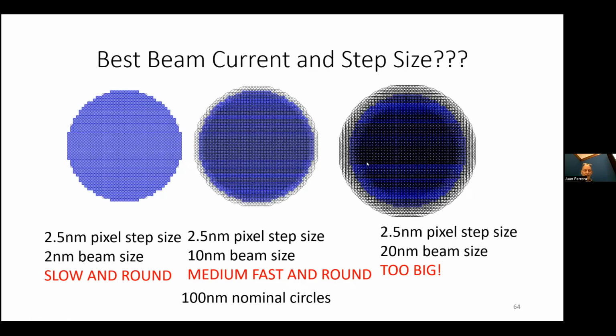Or in a kind of naive way, you could say, I'm going to use the smallest beam diameter I can, which is going to mean small beam current, and I'm going to use a tiny pixel size, and I wanted to define a 100 nanometer circle. We could do this. It's going to be round, although maybe we're going to see a little line edge roughness here, but it's going to be slow. If we increase our beam size, but maintain the pixel size, now we get this nice overlap. We probably round things up and we get higher throughput.